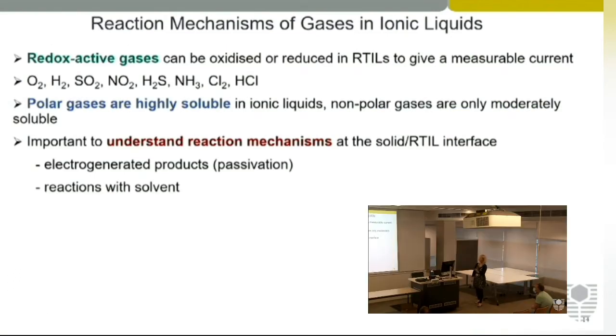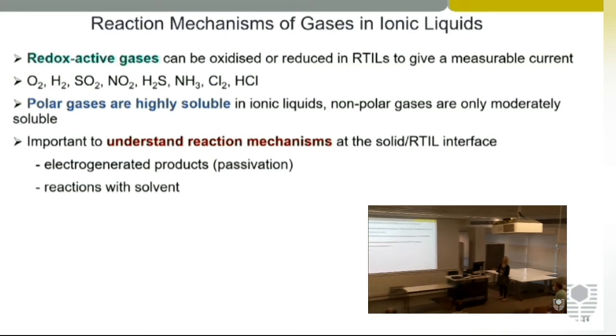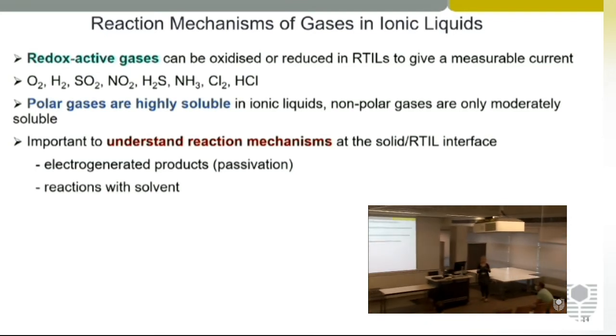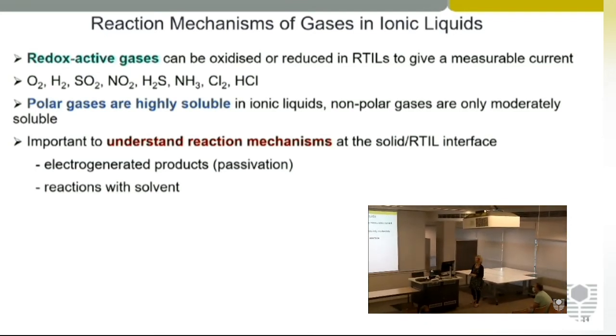I should mention that we can only detect redox active gases using our method. So we've done that using gases like oxygen and hydrogen, and we've also looked at a number of other more toxic gases. And generally, in terms of solubility, the polar gases are highly soluble, and these non-polar gases, oxygen and hydrogen, they're still soluble, but they're much more moderately soluble.